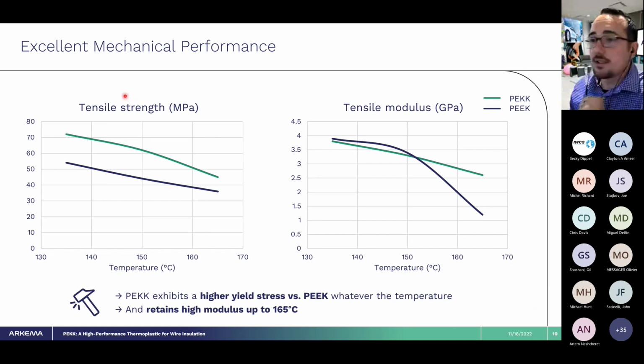What you've got on the left is the tensile strength, and on the right is the tensile modulus. The key thing here is we're looking at the elevated temperature performance of these materials. Both of these charts will go from 130 to 170 degrees C.